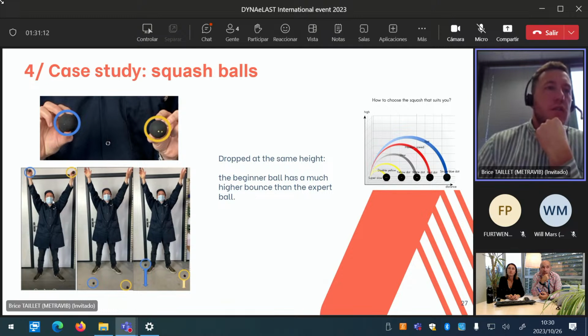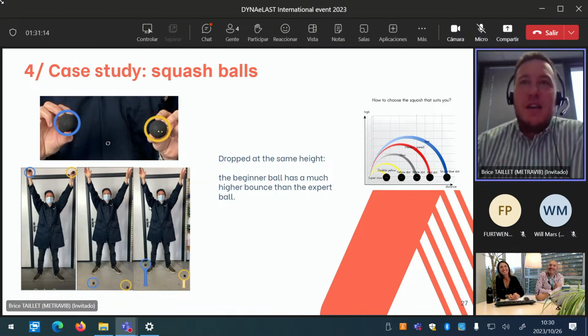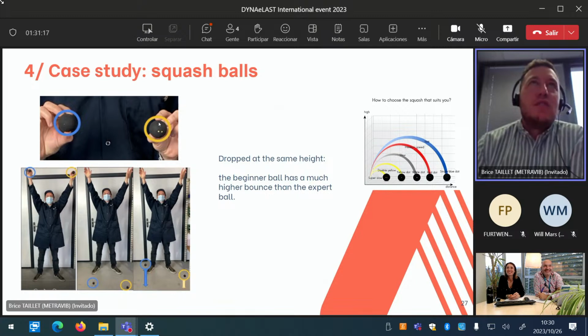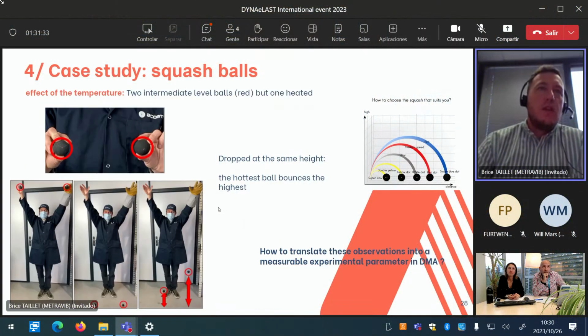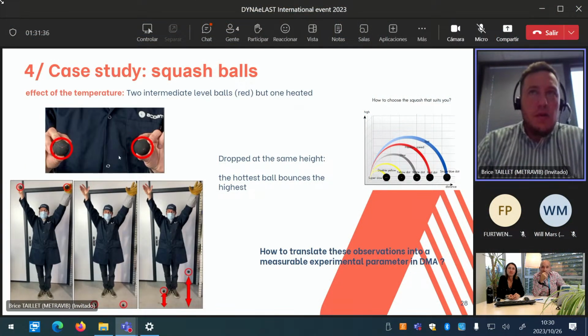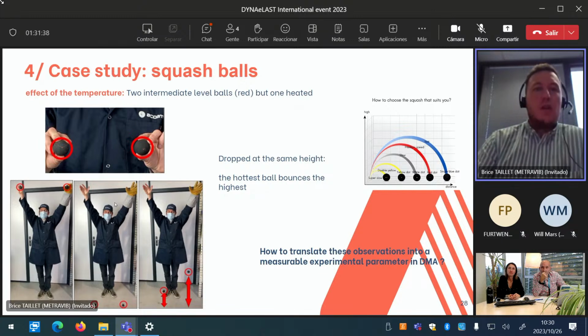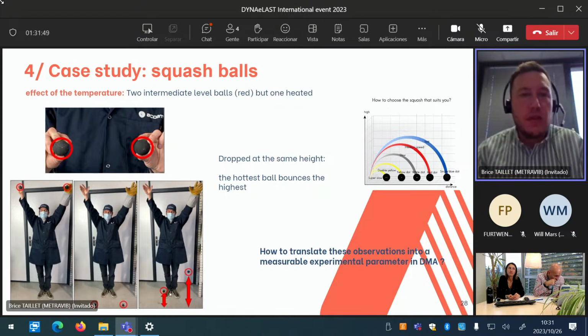I introduce you my dear colleague Mathieu. For this, we drop the beginner and the expert balls at the same height, and of course you can see that the blue one shows a much higher bounce than the expert one. Just to compare expert and beginner balls. If we compare the same ball but at a different temperature, we can see that the hottest ball, this one, the bounce is really high in comparison with the standard temperature one.